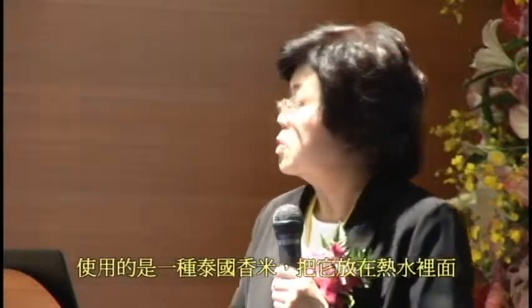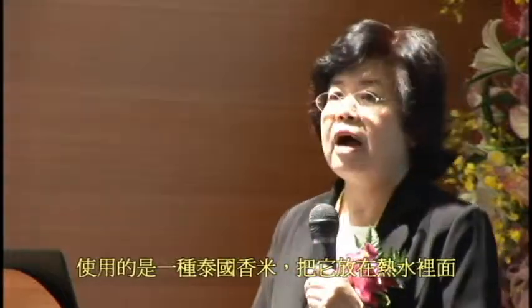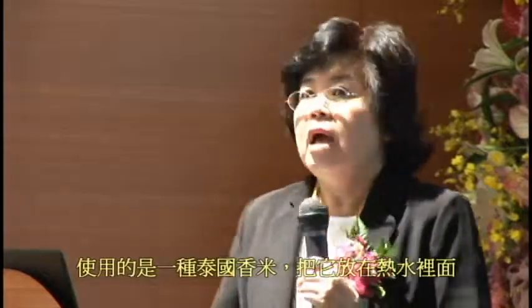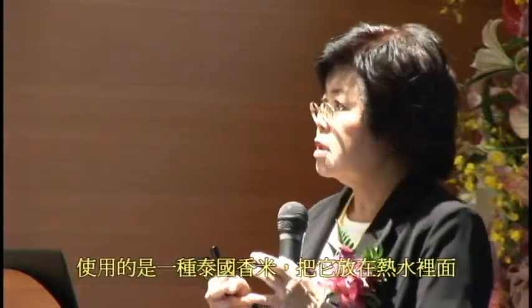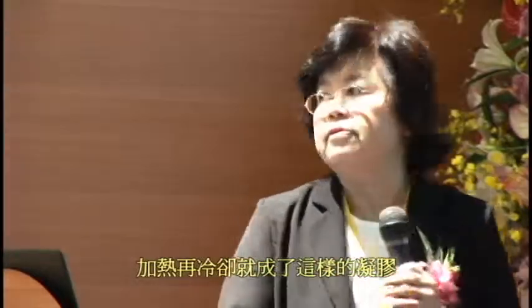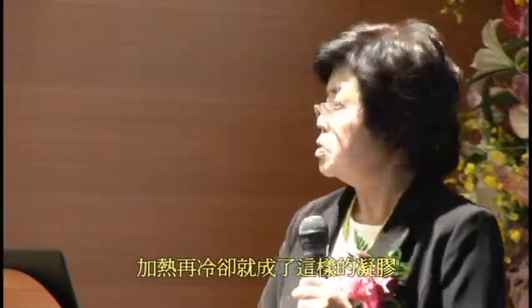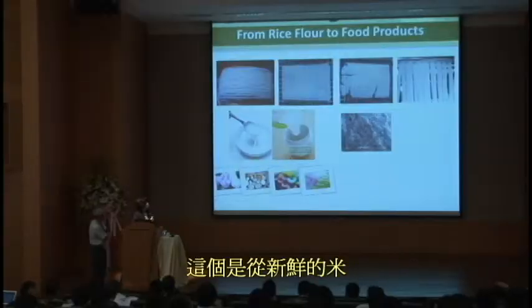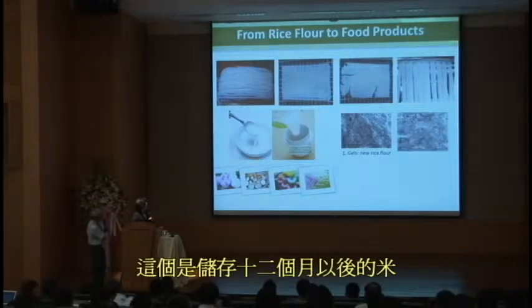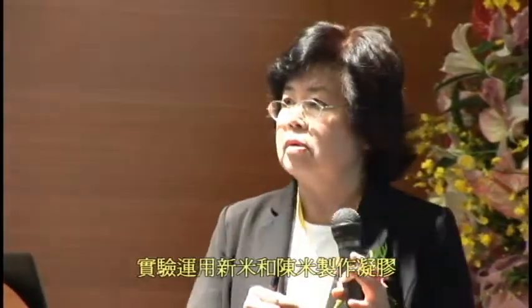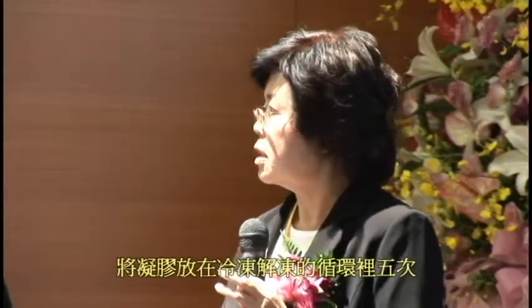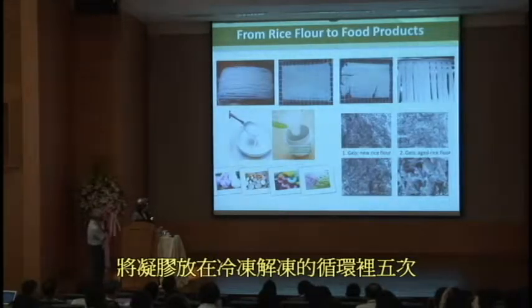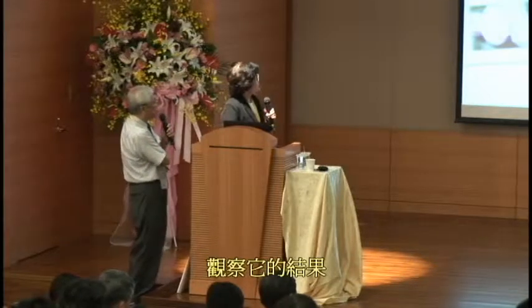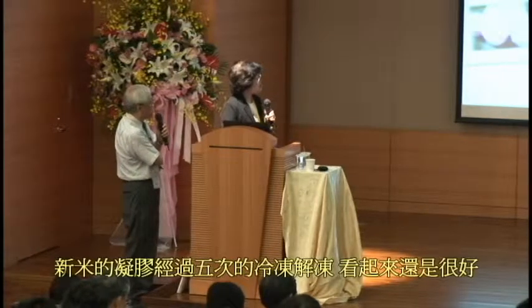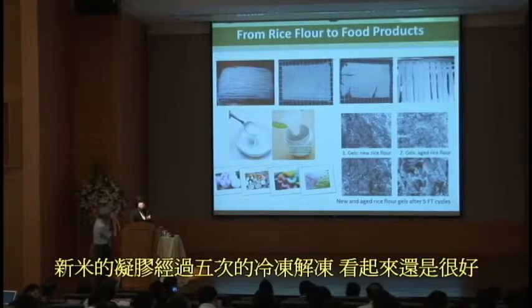This is a rice flour gel made from khao dok mali 105 or jasmine rice. It's an indica rice. We mix the rice flour with water, heat, and then cool down, and got this rice flour gel. Looking at the SEM, this one is from new rice, and the second one is the gel from the aged rice, 12 months. We subjected this gel to freezing and thawing for several cycles, and we found this. You can see that for the gel from the new rice flour, after 5 freeze-thaw cycles, the microstructure still looks okay.